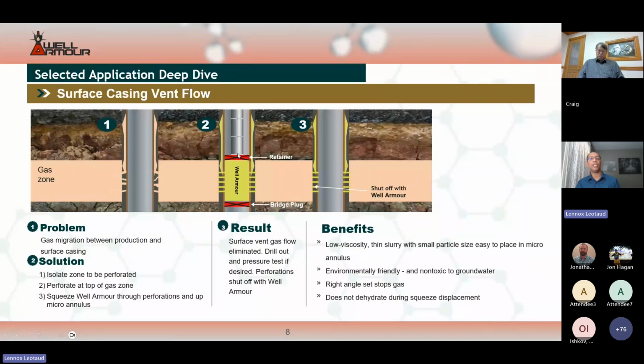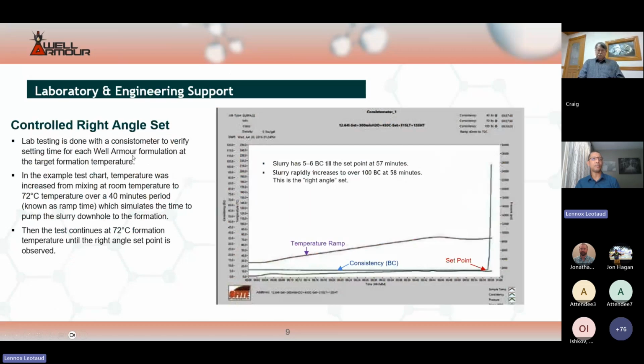Now, using a retainer or packer is at times a preferred method to utilize the Well Armour slurry, because in this way you're able to trap pressure below the retainer or packer, allowing you to leave pressure on the system, whilst the Well Armour is able to transition from a liquid to a solid state. And again, the benefits here, as mentioned earlier, also apply.